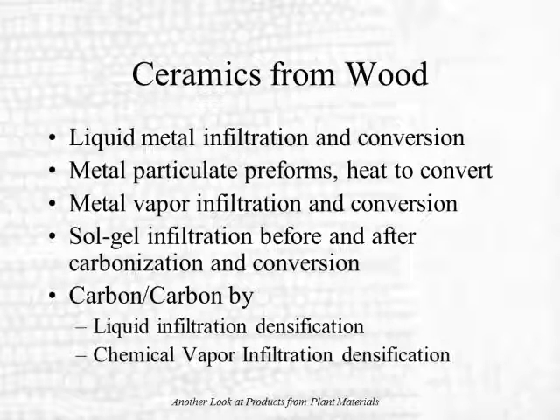You can do it by metal infiltration, liquid metal infiltration and conversion. You can do it by particulate metal preform, so you can make a compressed board with metal already in it, pressed board out of wood shavings, wood dust, wood flour, and you can form something like a medium density particle board with metal already in it, heat and convert that. You can use metal vapor infiltration at elevated temperature to convert the carbon into a ceramic. Use sol gel infiltration in the wood before carbonization or after carbonization, and the sol gel brings in with it the metallic elements that can combine with carbon or can exist after heat treatment to form a ceramic.